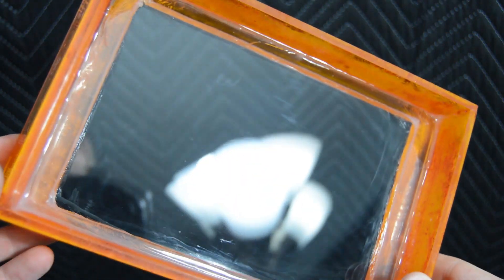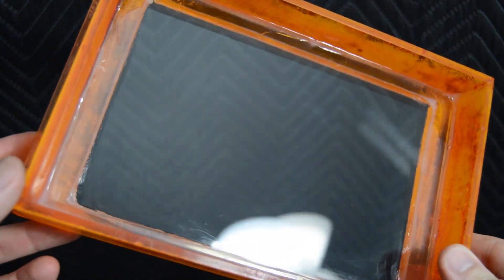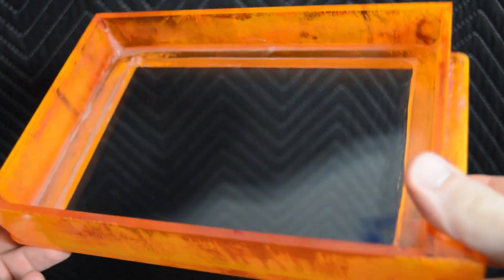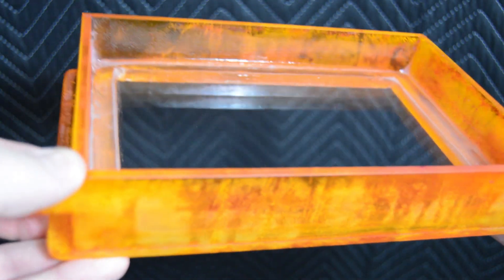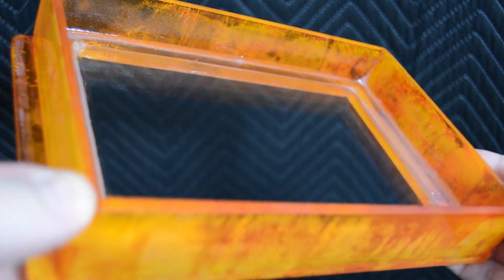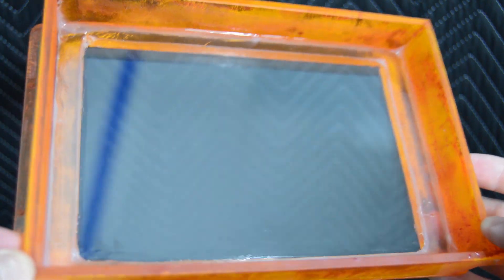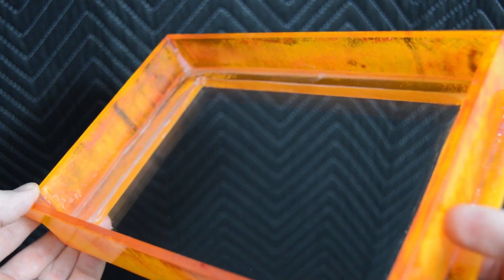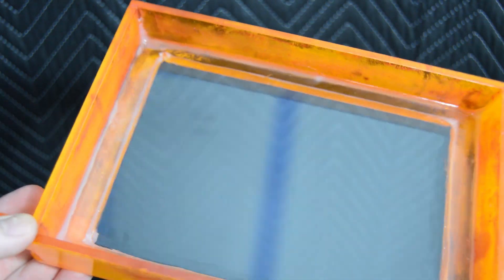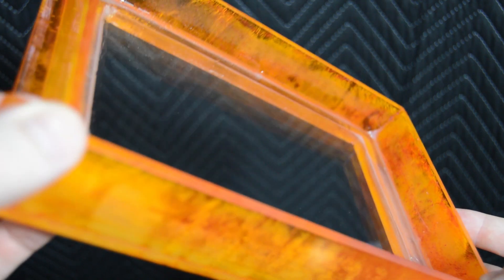Unfortunately, I discovered after the PDMS was cured that it has a very negative reaction to silicone. Therefore, I do not recommend that you use silicone at any point on the inside of your vat if you are intending to recoat it with PDMS. Basically, the cross-linking reaction was inhibited in the PDMS around the wall of my vat, where the silicone was located.